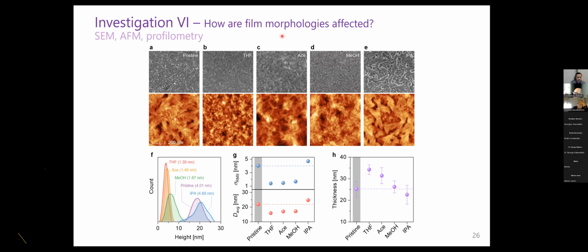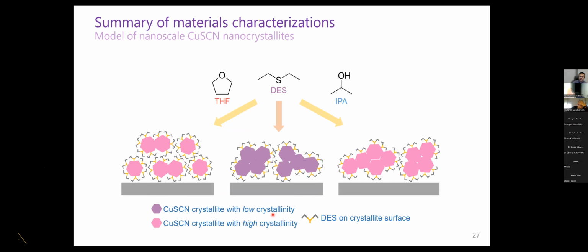And in terms of the film morphologies, with THF, even though the films become slightly thicker when we wash with THF, the RMS becomes smaller, so it becomes smoother, and also the grain size becomes smaller. So from taking all of the evidence together, we think what happens is this.